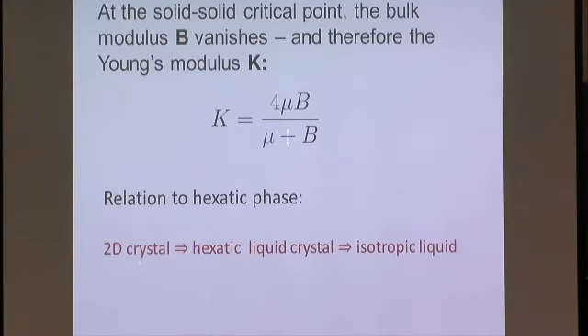So the scenario that you could have is that you have a 2D crystal. At some point you go through a transition where dislocations can spontaneously unbind, and you get a hexatic liquid crystal that is bond ordered, and then the second transition is needed to get you to the isotropic liquid phase, where you have short range bond order and short range translational order.